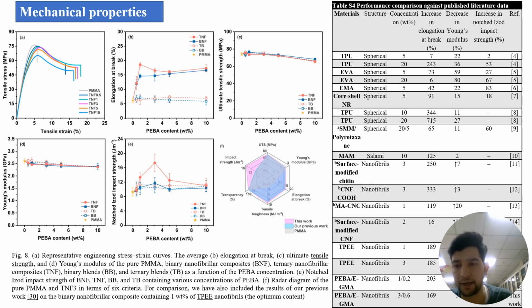Figure 8C and D show ultimate tensile strength and Young's modulus, which decrease with higher PEBA concentration, with TNF10 showing an 11% decrease in strength and a 10% decrease in the modulus compared to PMMA. However, TNF with low PEBA nanofibrils, only 3%, shows minimal changes in the strength and modulus compared to PMMA, similar to BNF, BB and TB.